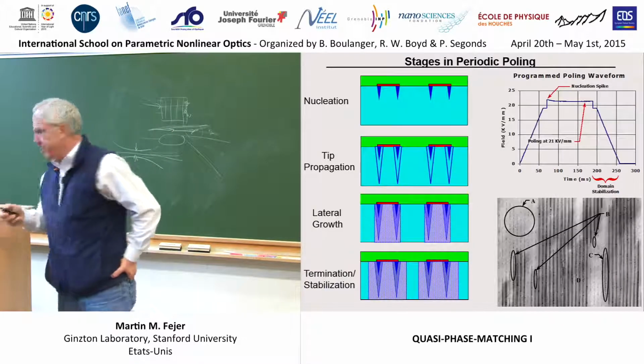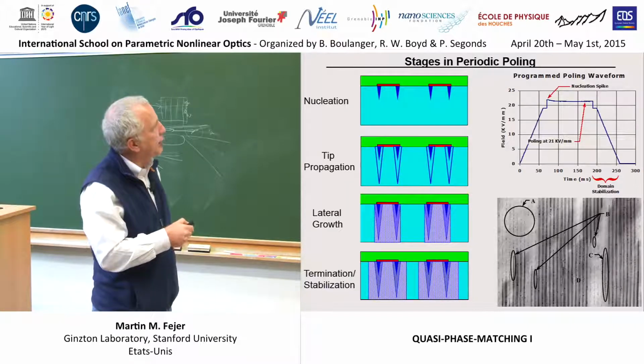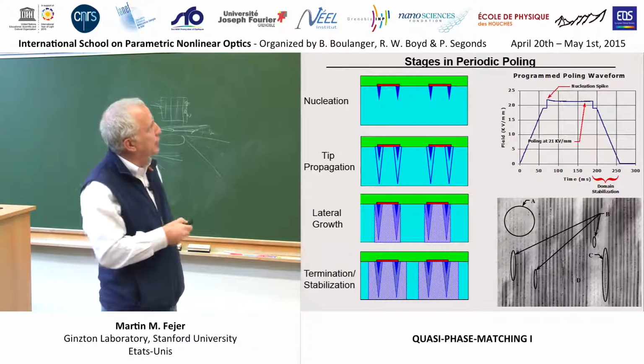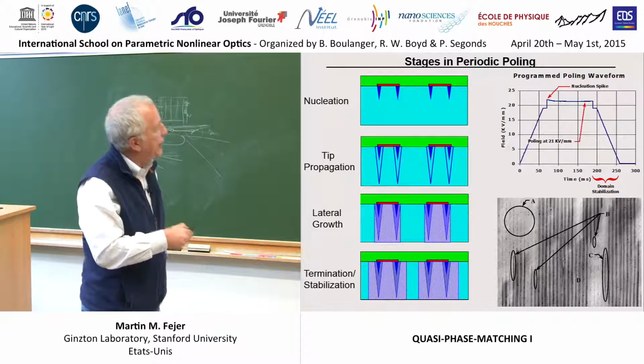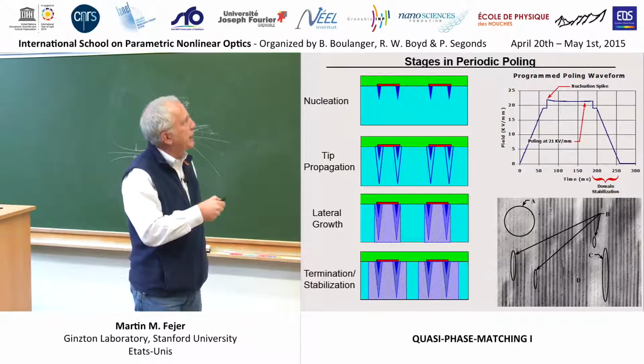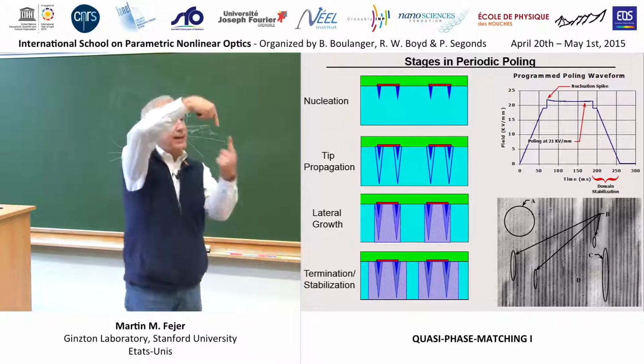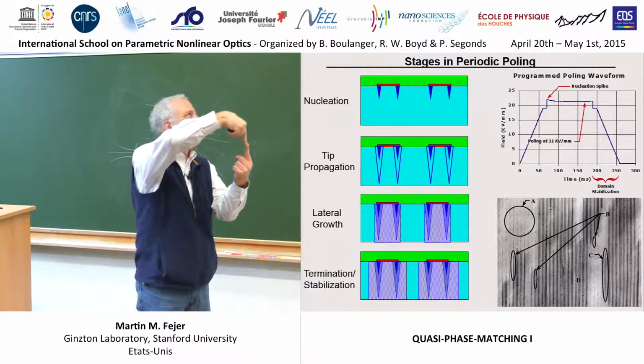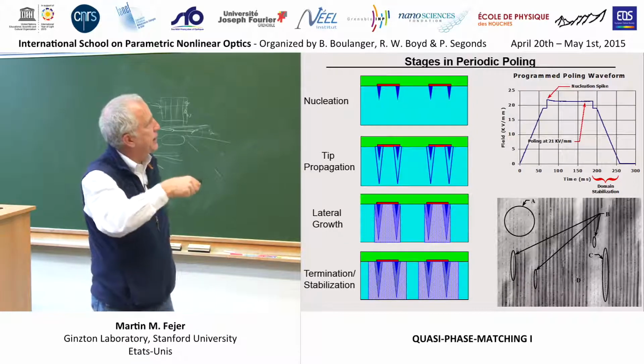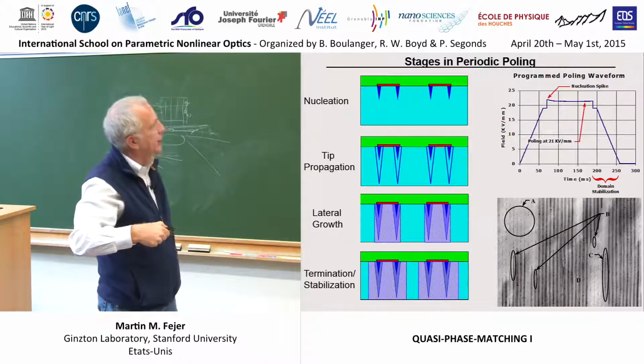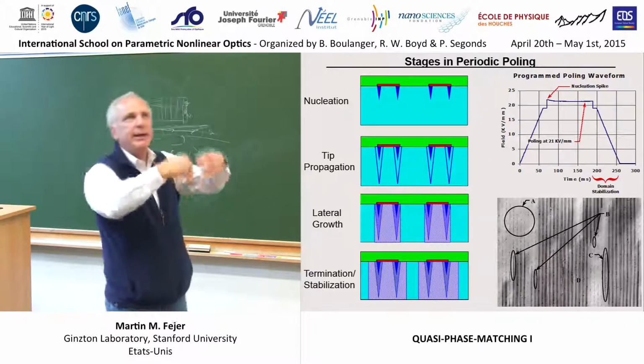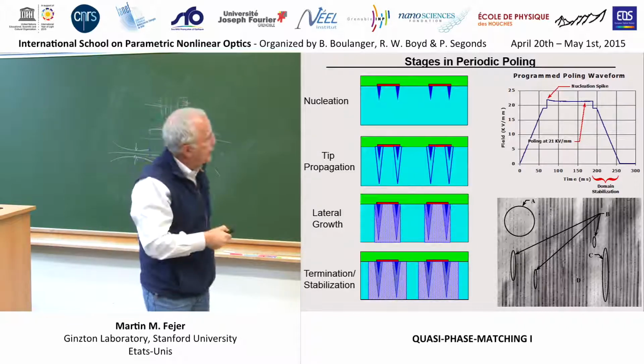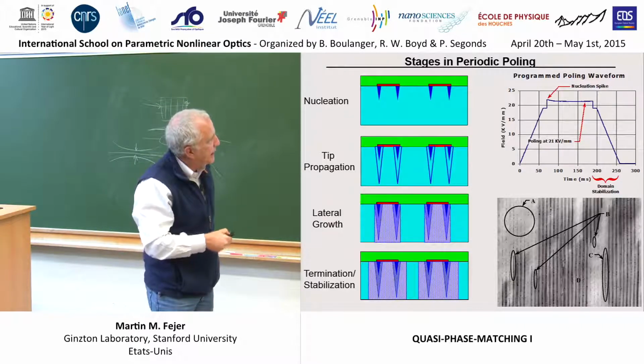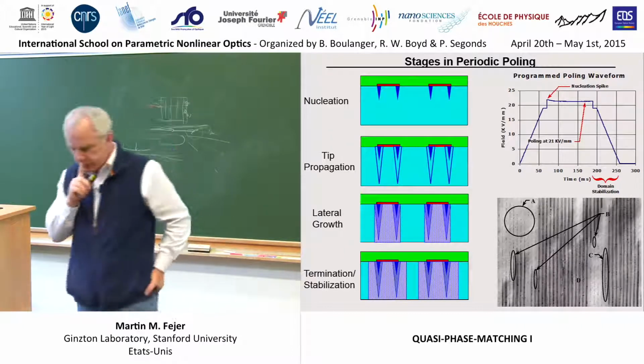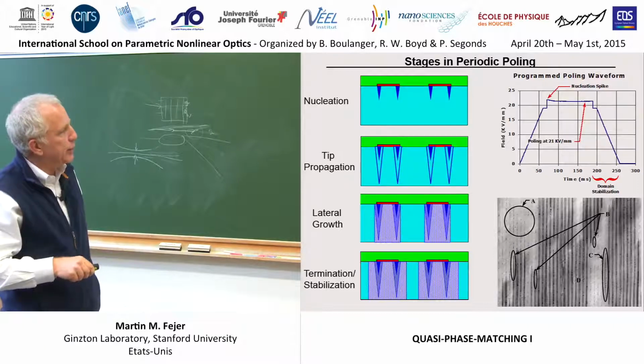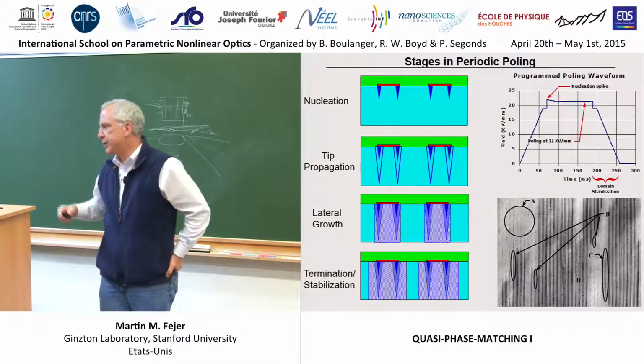So if you design this thing right, the process will start nucleating some domains in the fringe field regions at the edge of your electrode. Those domain nuclei rapidly shoot across the wafer. They don't like this situation because you've got head-to-head domains, and that's a very high energy situation, lots of bound surface charge at those interfaces. They shoot through to the other side. They quickly fill in under the electrode because that just aligns them with the field, reduces everybody's energy, everyone's happy. And then they try to keep spreading, but as we just discussed, as they spread past the edge here, they will stop themselves because they reduce the average field due to the unscreened polarization charge.